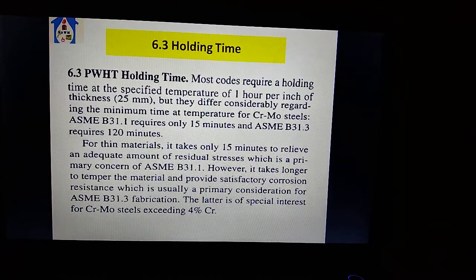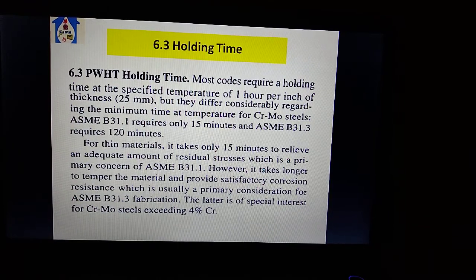Holding time. Most codes require a holding time at the specified temperature of 1 hour per inch of thickness, 25 mm. The thumb rule is 1 inch per 1 hour. But they differ considerably regarding the minimum time at temperature for chromium molybdenum steel. ASME B31.1 requires only 15 minutes and ASME B31.3 requires 120 minutes. For thin material, it takes only 15 minutes.